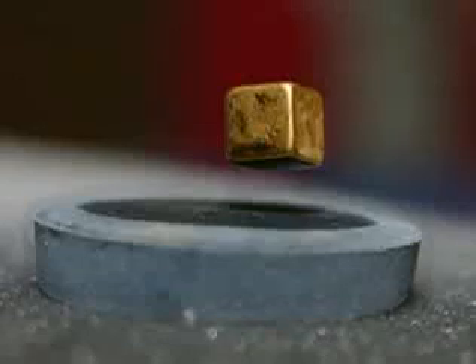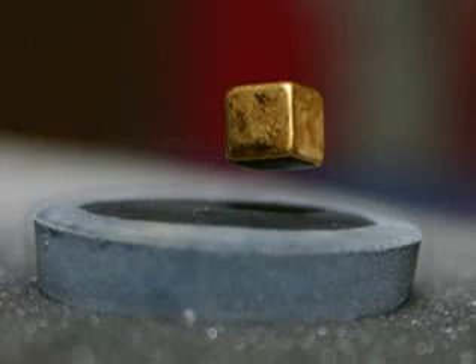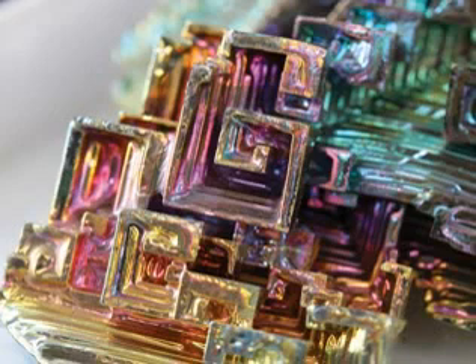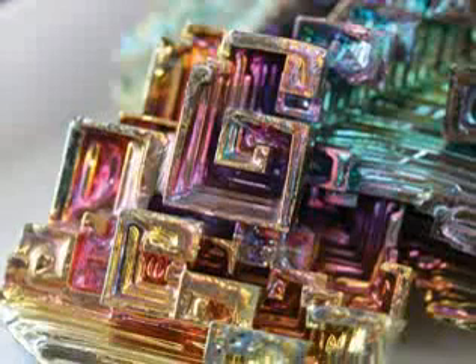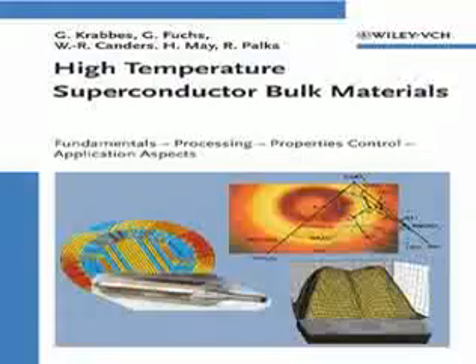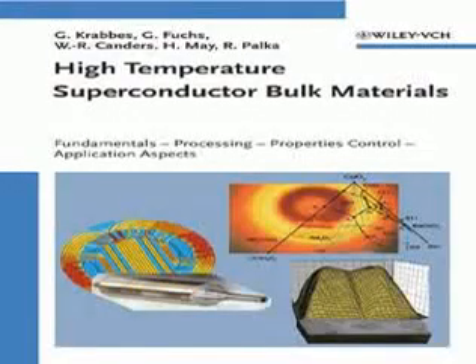The tapes are then reacted at high temperature to form dense, crystallographically aligned Bi-2223 multifilamentary conducting tapes suitable for winding cables or coils for transformers, magnets, motors and generators. Typical tapes of 4 mm in width and 0.2 mm thickness support a current of 200 A at 77 K, giving a critical current density in the Bi-2223 filaments of 5 × 10^4 A/cm². This rises markedly with decreasing temperature so that many applications are implemented at 30 to 35 K, even though Tc is 108 K.